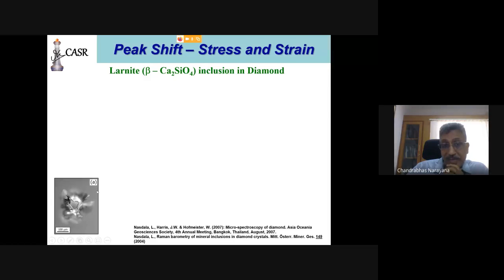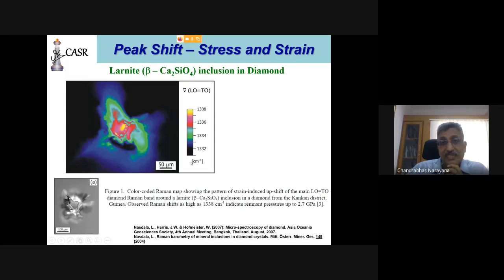So if I actually map this with 1332, I see that as you go closer to this larnite, you start finding that the 1332 peak becomes 1338. Now, why should it shift when it comes here, whereas it is 1332 here? All black is 1332, whereas yellow is 1338. Now, what is the reason why it happens?